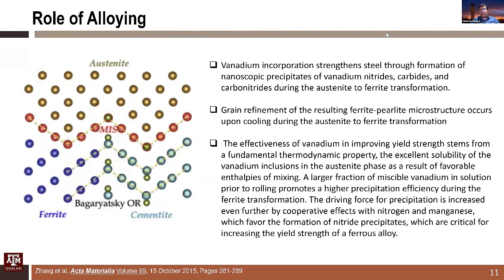So to take a step back, why do we do microalloying? Again, many people in this audience are very familiar with this. The reason we do vanadium microalloying is that it strengthens steel through formation of nanoscopic precipitates of nitrides, carbides, and carbonitrides during the austenite to ferrite transformation. And grain refinement is also something that you see during the ferrite pearlite transformation. And the effectiveness is really a very beautiful thermodynamic property of vanadium, the excellent solubility of vanadium inclusions in austenite. As a result of the enthalpy of mixing, you have a lot more miscible vanadium in solution prior to rolling, and you can work at some pretty reasonable temperatures as well. So this is really the reason for using vanadium microalloying.